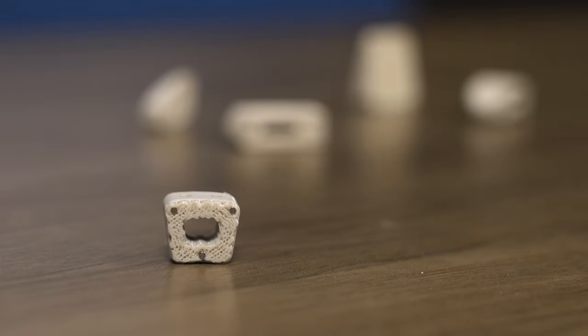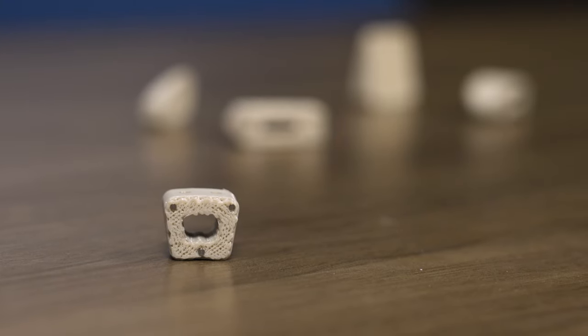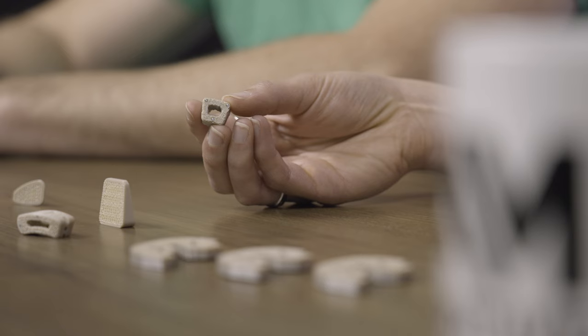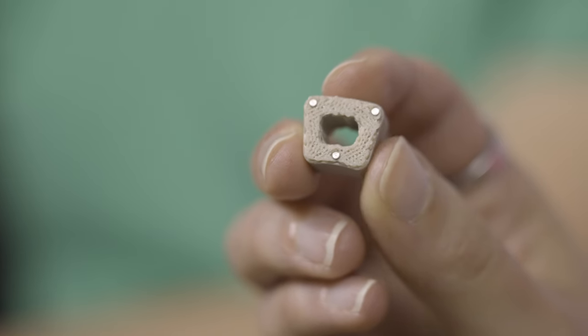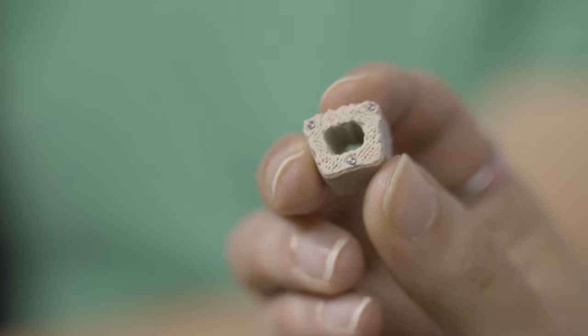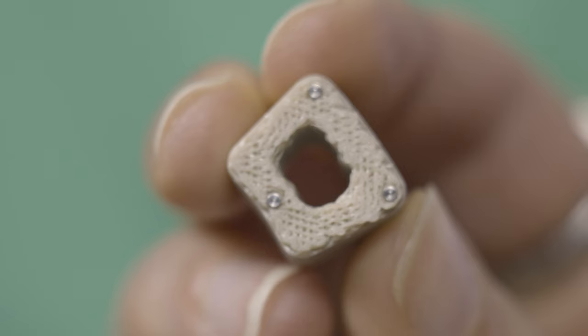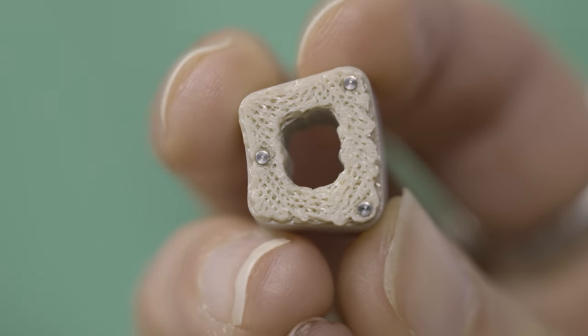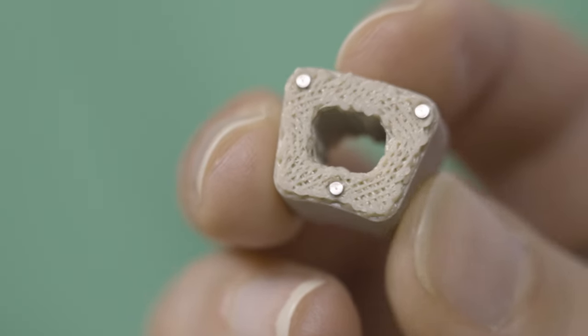We want you to test this without your metal markers in there. They might be strengthening it. Or we want you to do testing above and beyond what those standards call for. Now, of course, we were a little concerned about doing so, but we did. And in fact, our mechanical properties didn't change, which demonstrates to us that our Z-layer bonding and our control of our internal structures is really quite robust. And the mechanical strength and the process qualification demonstrated a very, very tight process.